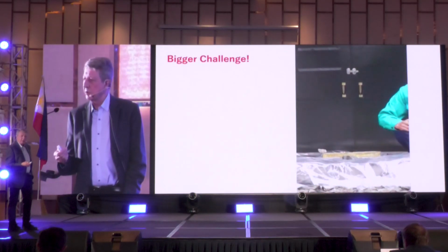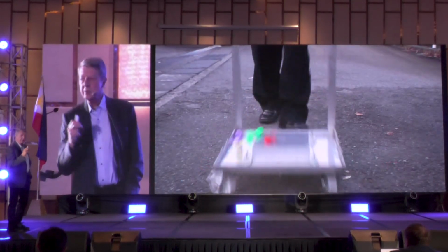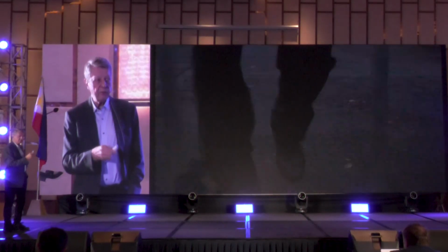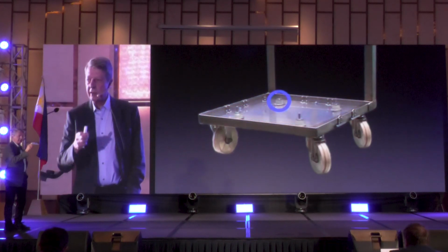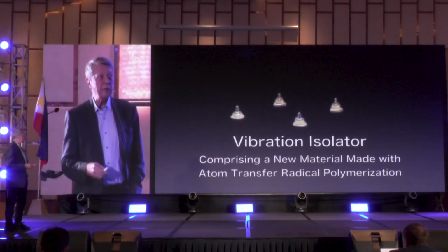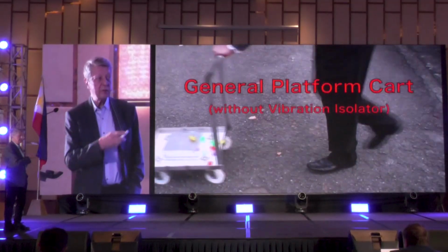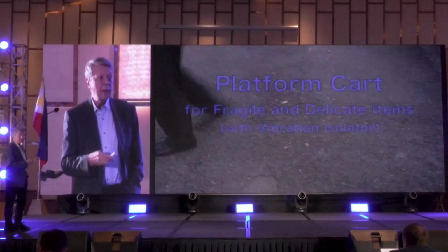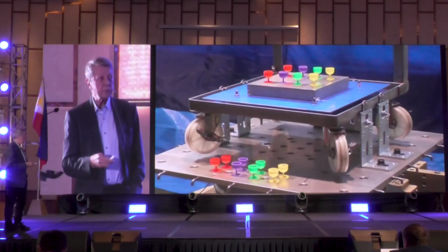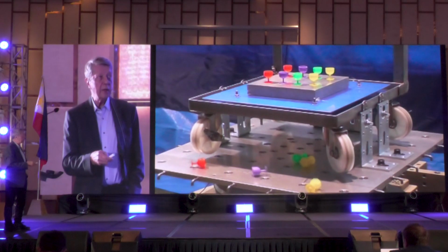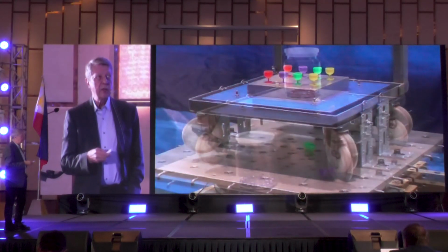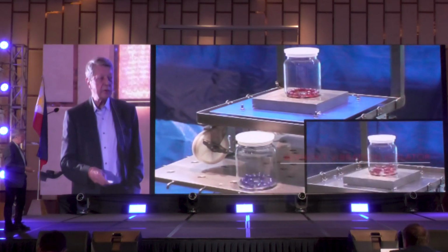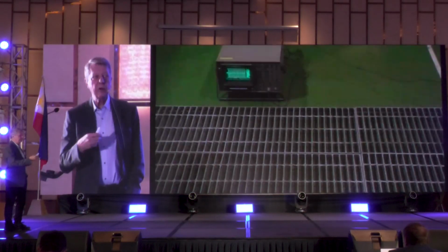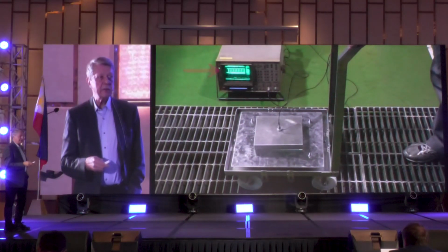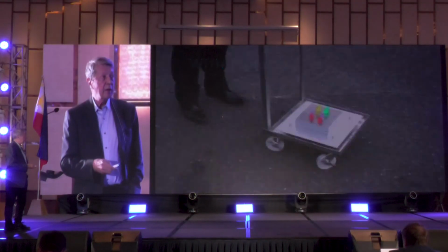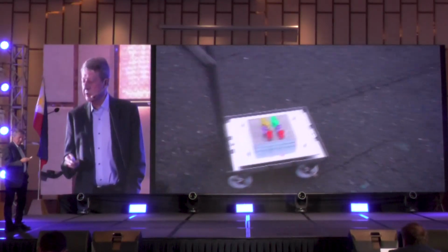So what can it be used for? One example is shown here: to transport very delicate things on a rough surface. You could see if you use the polymer here, which would be like a pad of 1 inch maybe in size, it would isolate all of this vibration. And in that case, this is what happens without this vibration isolator and what happens with the vibration isolator. Dramatic change. You could see here what happens without isolator and with isolator. And you can do the same sometimes also with glass or metal bearings, without and with isolator. And you can even quantify that by moving this cart on a rough surface. You could see oscillations which are coming with and without isolator. And now you can transport these goods in a much more efficient way.